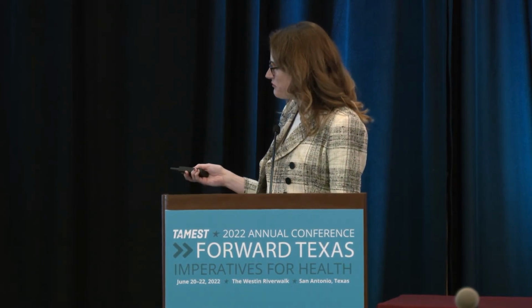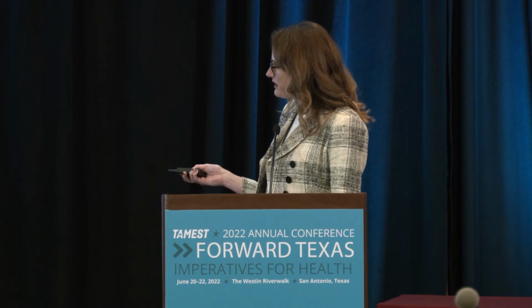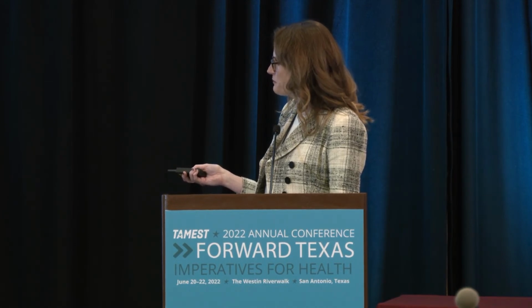So from this knowledge, we've continued this study with many other systems. We've defined an operating principle for these polymers, which is that swelling of the polymer electrode is beneficial to enhance kinetics and performance. It allows you to charge and discharge the organic battery faster. It improves the cycle life, and it also improves the stability and the capacity.